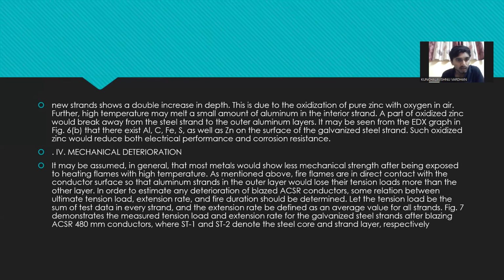Mechanical deterioration. It may be assumed in general that most metals would show less mechanical strength after being exposed to heating flames with high temperature. As mentioned above, fire flames are in direct contact with the conductor surface, so that aluminum strands in the outer layer would lose their tension loads more than the other layers. In order to estimate any deterioration of blazed ACSR conductors, some relations between ultimate tension load, extension rate, and fire duration should be determined. Thank you.